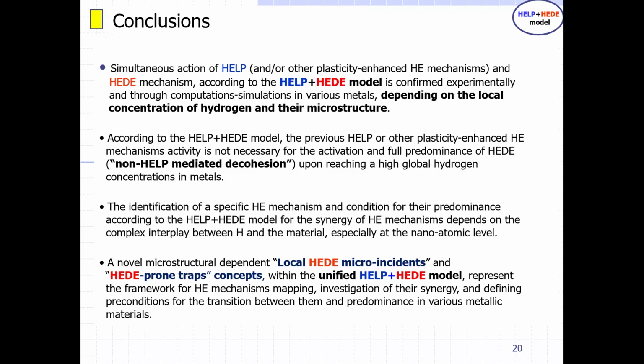To see that when you have a high hydrogen concentration, you need to map the hydrogen distribution in the microstructure, and then measure the local hydrogen concentration and show that we have high, medium, and low local concentration. There is a big problem with how to do that. But the novel microstructure-dependent local HEDE micro-incidents and HEDE-prone traps concept within the unified HELP HEDE model represent the framework for hydrogen mechanism mapping and further investigation of their synergy, and for defining, what is very important, the precondition for the transition between them, which means when we can safely use some components exposed to hydrogen and when it will fail in a brittle manner due to HEDE predominance. So, brittle failure by hydrogen embrittlement happens immediately and it's very dangerous. Thank you very much for that.